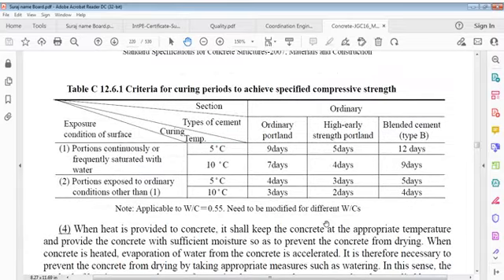As said before, exposure conditions: portions continuously or frequently saturated with water, and portions exposed to ordinary conditions. Type of cement, first of all we have to see, and temperature column 5 and 10. Ordinary Portland cement is 9 days, 7 days, 4 days, 3 days, and high early strength cement is 5, 4, 3, 2 days. Blended cement 12, 9, 5, 4. Water cement ratio is 0.55, need to be modified for different water cement ratios.